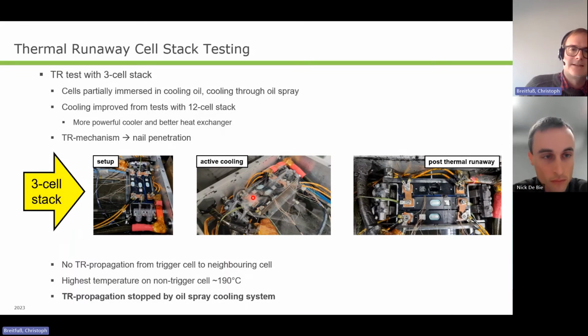We had three cells here, and we sent the first cell into thermal runaway via nail penetration, and the result was very good. We only had one cell in thermal runaway. You can see it here, with the open vent. It's nice. The cooling oil spray washed everything away from the thermal runaway, so it looks quite clean. And you can see the other cells are still healthy and still working. The highest temperature on the next cell was 190 degrees at maximum. So it's a very optimistic and very good result.